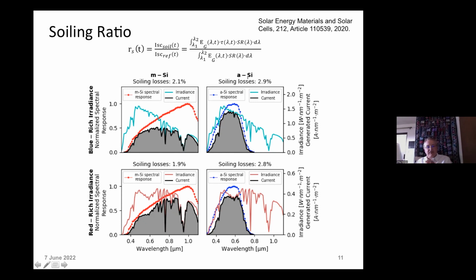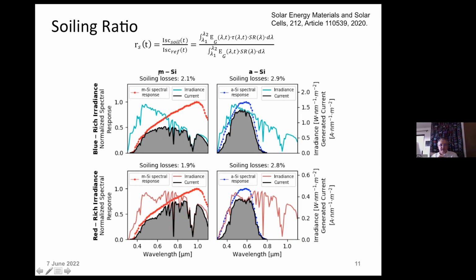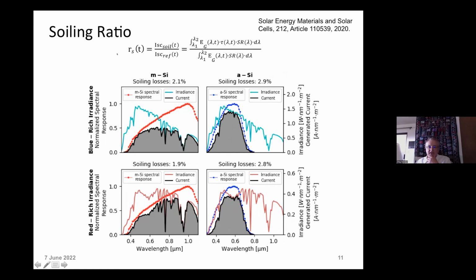If we have an amorphous silicon solar cell next to the multicrystalline solar cell, I can have different soiling losses because it has a different spectral response: 2.9% in the case of the blue-rich spectrum, and 2.8% for red-rich. So the soiling loss can be different for different types of materials. Ahmed mentioned pyrite. If I had pyrite here, it might be closer to here. If I had cadmium telluride, it might be somewhere in the middle between amorphous silicon and multicrystalline silicon. So when you're thinking about soiling, you really need to consider this integral: the transmission, the spectrum, and the spectral response.